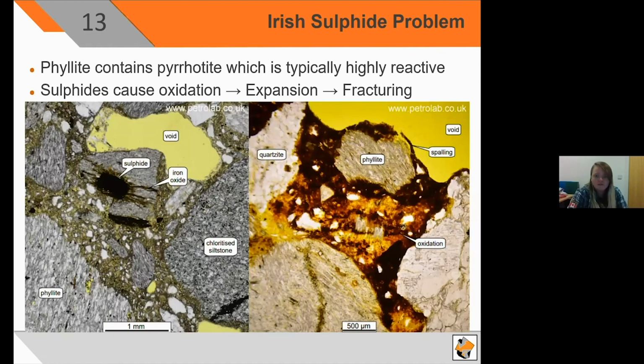So here's some typical photos which actually look quite similar to the Mundic ones that I just showed you. So this is the Donegal phyllites. It contains pyrrhotite, and on the picture on the left, you've already got a sulfide with a little halo starting to oxidize and radiate through the fractures. And then on the right, you've got an extreme example with a brown oxidation through the binder, causing the linings to spall around that phyllite fragment there.